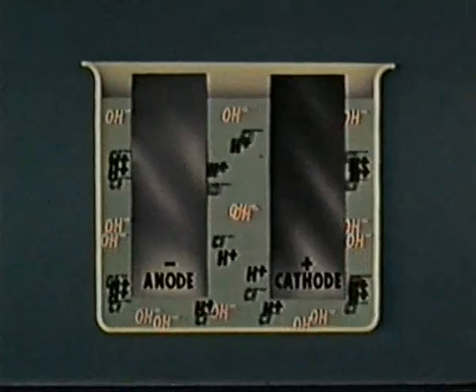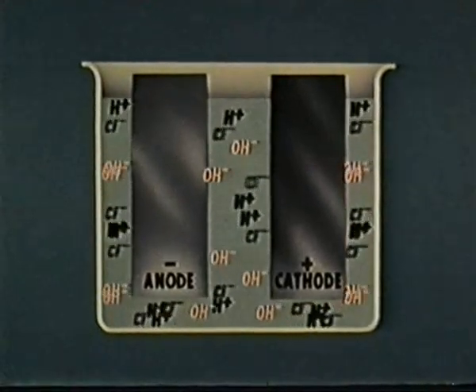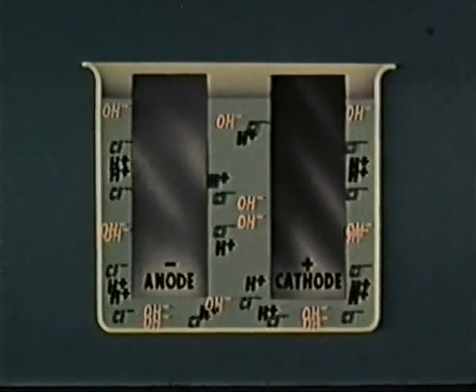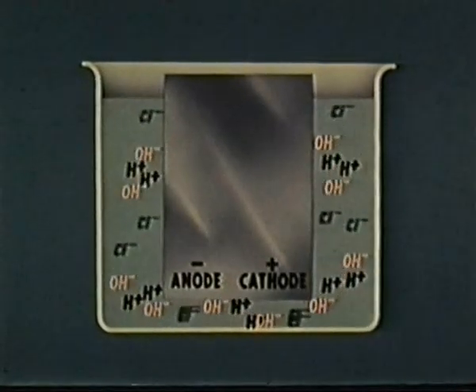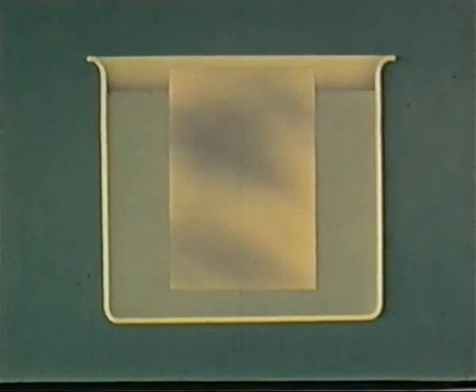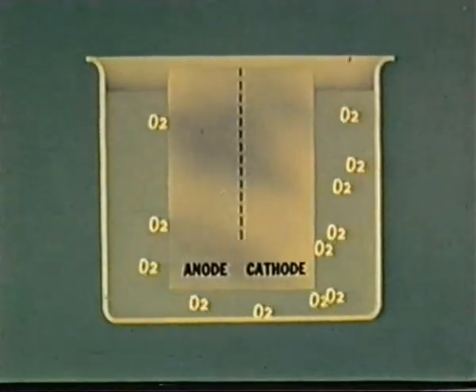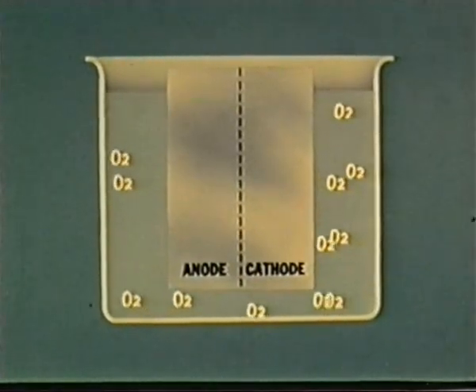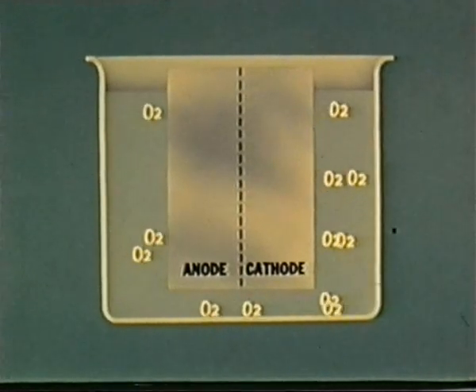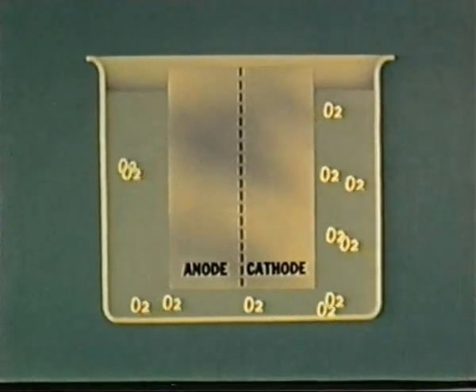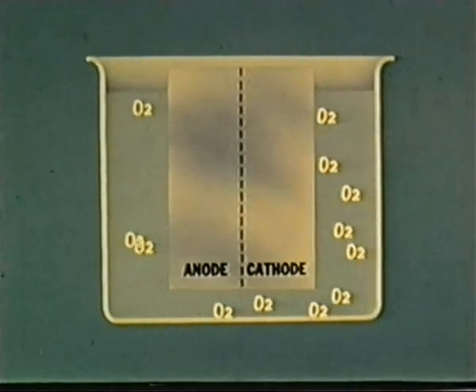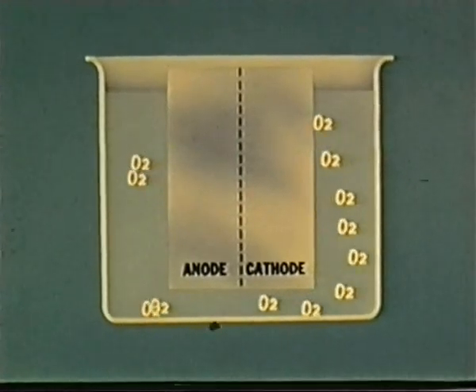The same type of cell that develops between two different metals may also develop on a single metal surface. Differences in potential from point to point can be created by differences in environment. Oxygen concentration cells can be set up to cause cathodes to develop at the areas of high oxygen concentration, and anodes where corrosion occurs at the areas of low oxygen concentration.